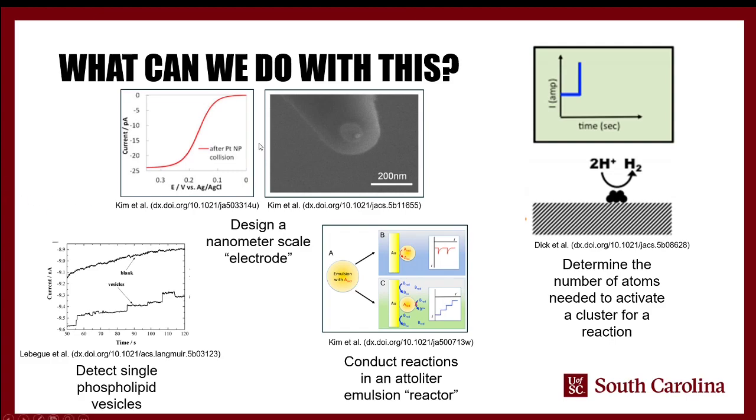And you can actually see there were 2 different variations on this. In the first case, they put the insulating layer on, but kept it thin enough, about 1 to 2 nanometers, such that it completely inactivated the disk electrode, but when a metal nanoparticle came into contact, it established a tunneling junction. And so you had a metal insulator metal junction where the only place that electrochemical activity could happen was on the platinum nanoparticle that was attached to the electrode tip. And so they were able to demonstrate that they could do that. In this case, it was about an 80 nanometer particle.